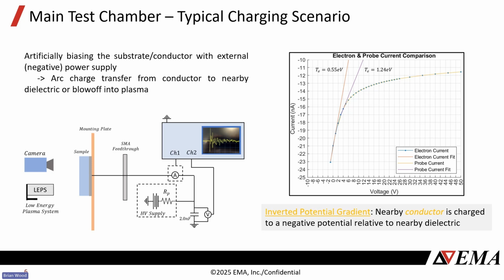And so how we simulate that in the lab, one way of doing it is essentially you've got your sample mounted. It could be some dielectric with a conductive substrate or a conductive frame or whatever it is. And now you are directly biasing that substrate of the sample with a high voltage supply, biasing it negative to represent how it would charge in the environment if it was GEO. And simultaneous to that biasing of the substrate, you are then exposing the sample to some plasma or some low energy electron exposure to neutralize the front surface of that sample. And so the LEPS is a really good source for doing that.